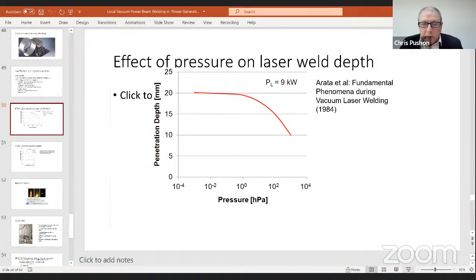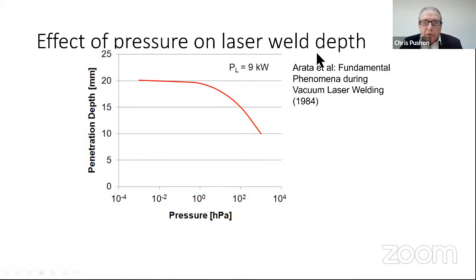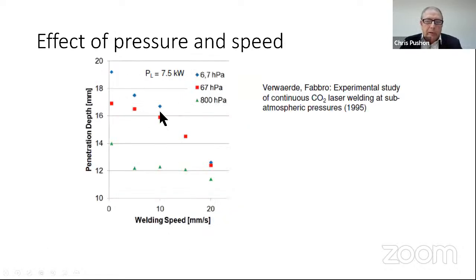Sorry about that. So what this shows is the effect of pressure on laser weld depth. Basically at 10^3 hectopascals, which is the same as millibar, with 9 kilowatts, we get 10 millimeter penetration. If you go to 10 to the zero, which is 1 millibar, we get double the penetration depth. And many people have shown a similar thing. This is atmospheric pressure, and this is a very coarse vacuum. So you get a lot more penetration for your money.